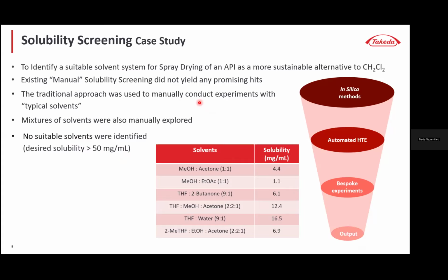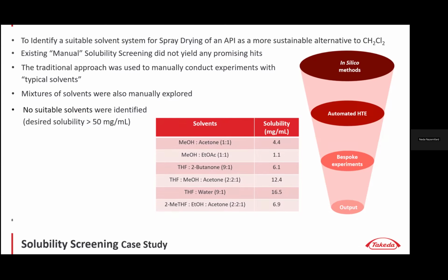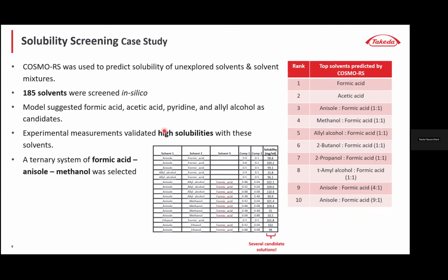So the traditional approach was to manually look at some of these experiments in the lab, and we didn't find a really good solvent from the typical solvents that we usually test. We also looked at mixtures of solvents, and they were manually measured for solubility, but again, no suitable system was found. So here is really where we went through our workflow.